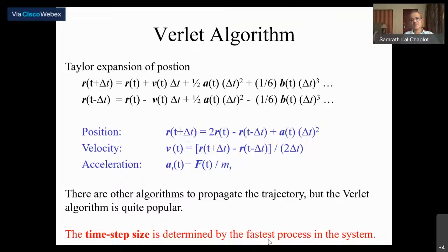So even if it's an amorphous structure, you have, let's say, the highest frequency vibrational process which occurs in either the same structure or a similar crystal structure, and you can get the same order of magnitude from any of the equivalent physics process. You use a time step which is something like 20 times smaller than the time period of the fastest process. So if the fastest process corresponds to say 10 terahertz, then the period of vibration is 0.1 picosecond or 100 femtoseconds, and so the time step could be something like 5 femtoseconds or smaller, which would be good enough for that example.